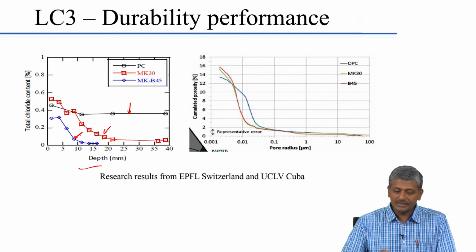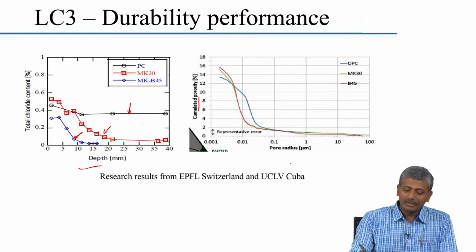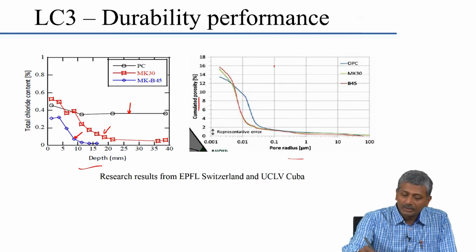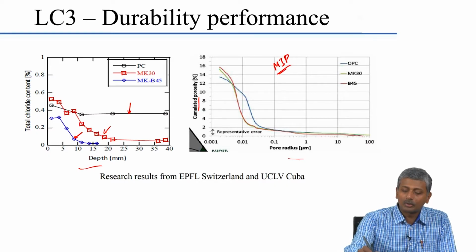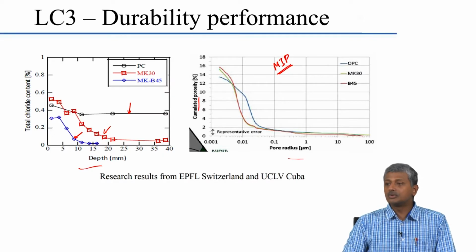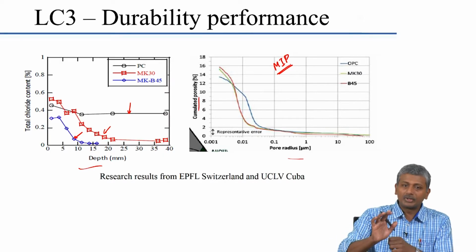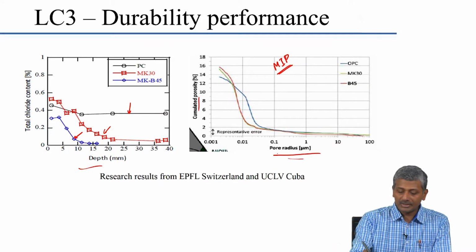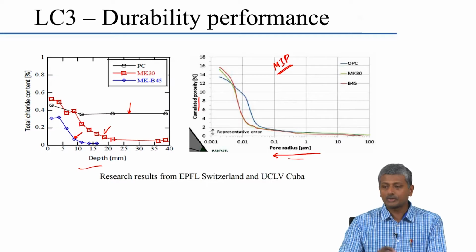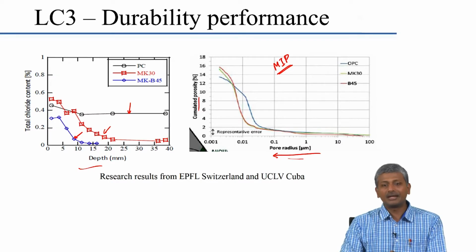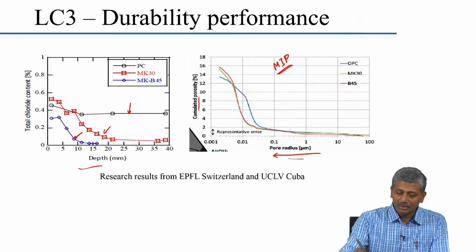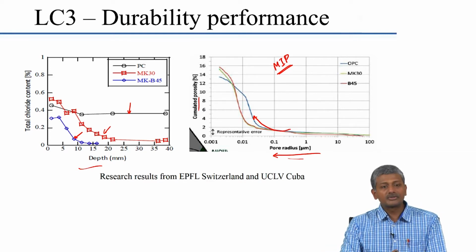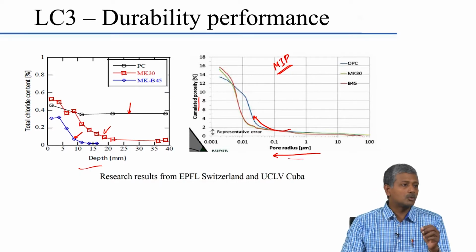Once again, this is the porosity expressed in terms of the pore radius. This is basically the graph that you get when you do the mercury intrusion porosimetry study that we talked about earlier. As you put more and more pressure on the mercury, it keeps intruding smaller and smaller pores, so the pore radius is decreasing in that direction, which means you are increasing the pressure in the same direction. As you increase the pressure, more and more of the pores start getting filled up, because with higher pressure the mercury will be able to intrude into smaller pores.